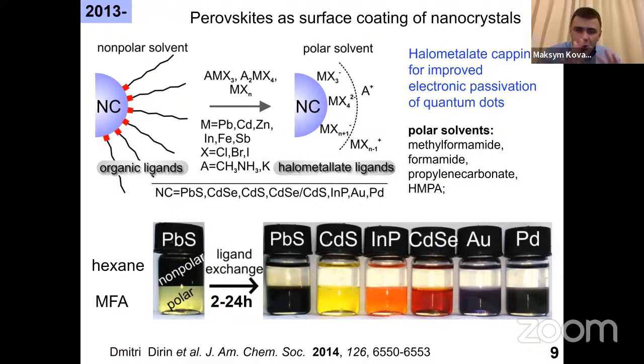So why don't we use them now as a coating for conventional quantum dots? So we take a perovskite as a shell to coat the conventional quantum dot instead of using the core shell strategy. And so that was super exciting because we were able to use these soluble forms of these perovskites, they are called halometallates, to use them as a surface capping ligand. So we displace organic ligands, we cover the surface with this halometallate coating. And because of that, we could basically fully change the surface functionality from apolar to highly polar.